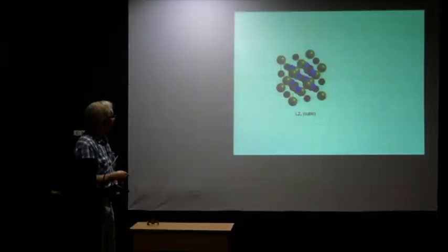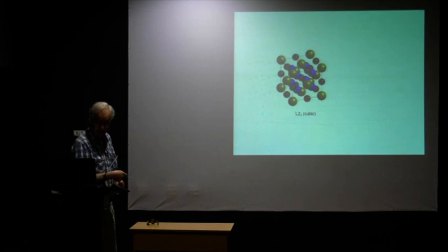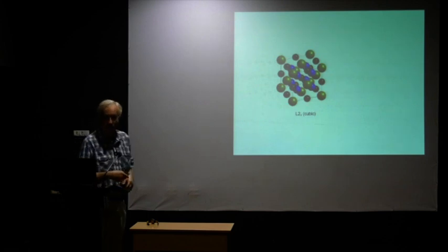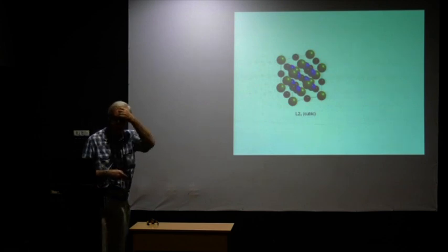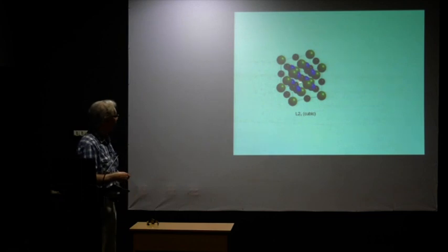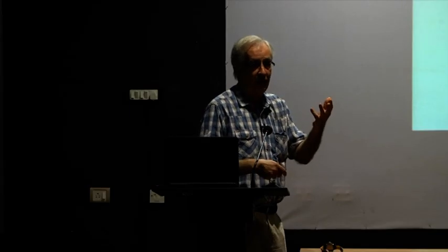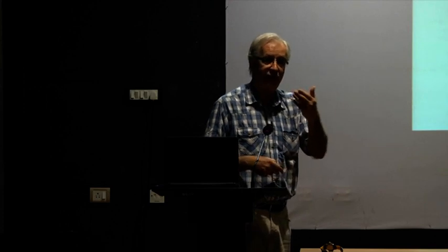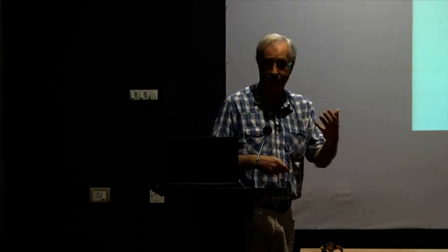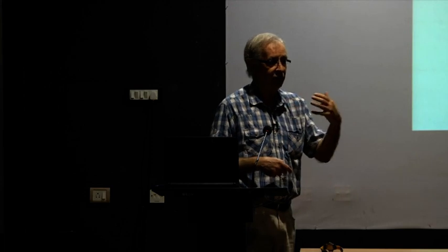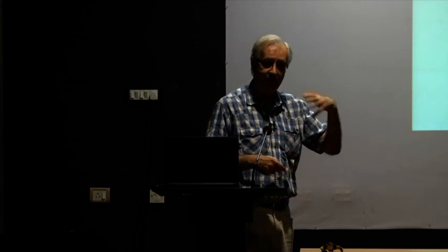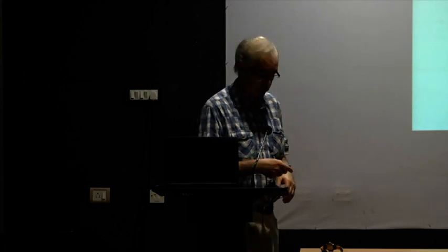The colors over here, there is a little contrast here, okay? So anyhow, this is the cubic structure, okay? This is the so-called L21, which we just saw. Of course, this is for the 50-25-25 stoichiometric case. The moment I go off stoichiometry, we have the L21, but then we have some disorder in there as well.